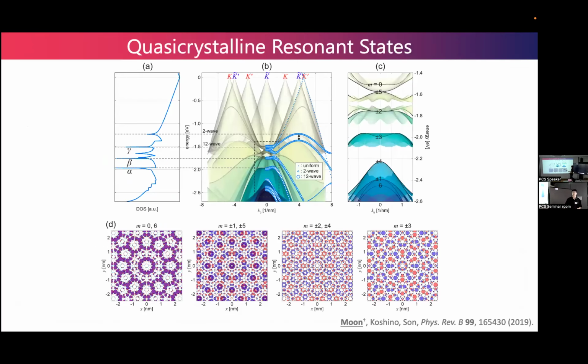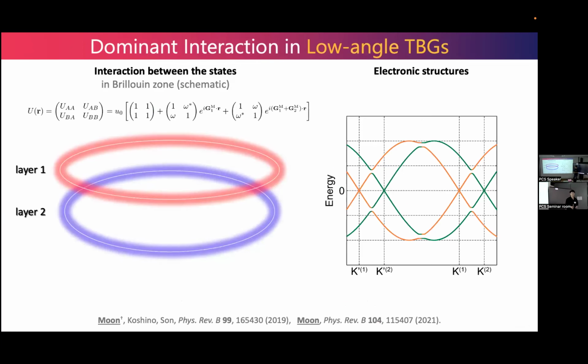And we calculated the band structure. Since this is still twisted bilayer graphene, we only have 4 independent Dirac cones, 2 from the upper layer, 2 from the lower layer. However, because of the geometry, 12 Dirac cones gather at a single point in the momentum space and form a new series of band structure. And here is the wave function in real space, which satisfies the quasicrystalline symmetry.